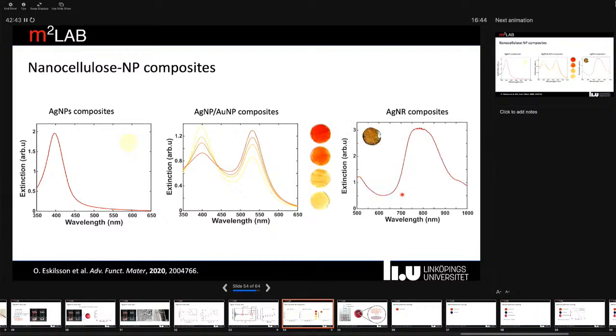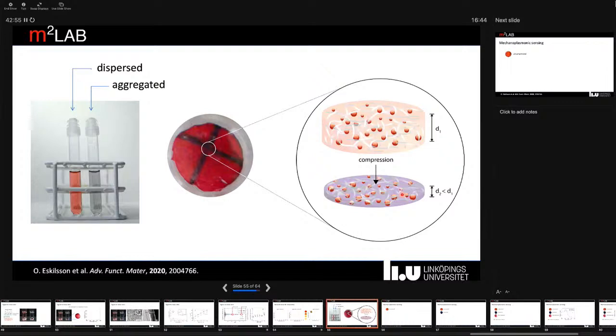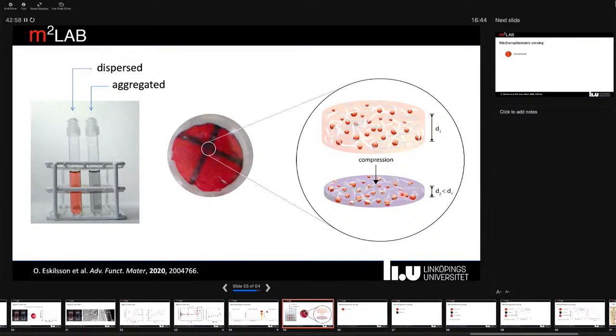immobilize all sorts of different kinds of particles, or a combination of particles as well, to do more elaborate nanoplasmonic materials. So that we thought was quite interesting, but something that really caught our attention was what happened when we subjected these composite materials to a bit of mechanical pressure. Then we saw that we got a change in color similar to what we see when we aggregated particles. But when we looked at these in the electron microscope, the particles were still fairly well separated. There was no difference here.